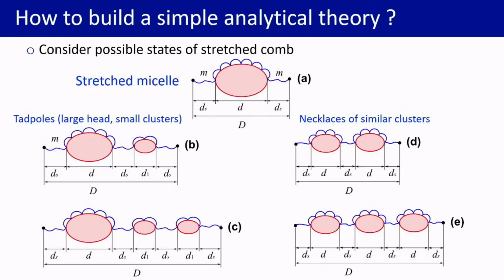So we were also able to develop a simple theory. In order to do so, we consider all possible states of the stretched macromolecule, the stretched micelle, tadpoles with a big head and small globules on the side chains, but we have also considered an alternative structure where the micelle is divided into clusters of equal size.